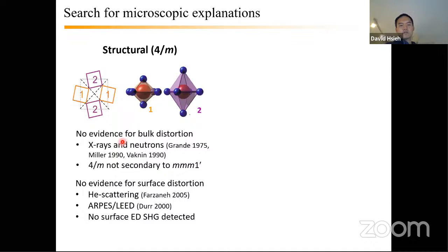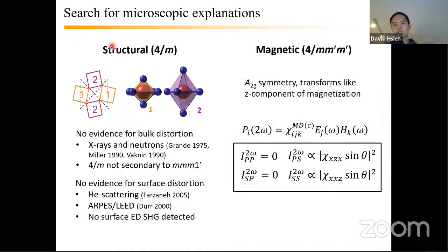You can posit that maybe there's some surface reconstruction, but again, surface sensitive techniques, helium scattering, ARPES, LEED, have not reported evidence of any surface reconstruction. And moreover, if it were only a surface reconstruction, you'd expect that we would pick that up through a surface electric dipole channel. But the fact that our signal vanishes at normal incidence tells us that it's not surface electric dipole radiation. So this maybe simpler picture of having just structural deformation lead to the loss of vertical mirrors is something that we rule out. The next interpretation is that it's some magnetic order that breaks these vertical mirrors.